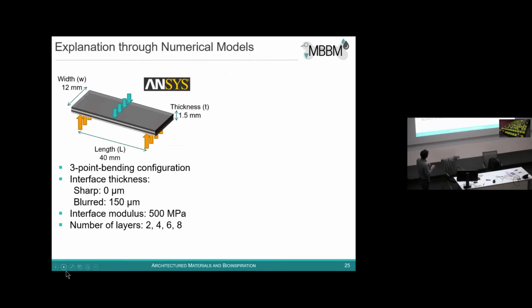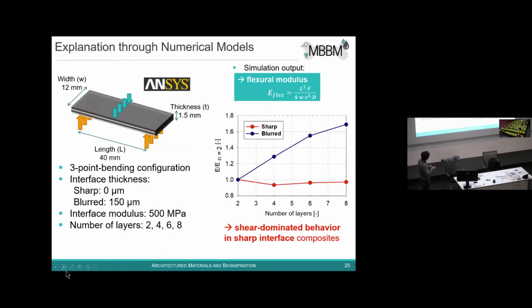So to understand this, we did some finite element simulations. We translate our system into a virtual material. We did finite element analysis, replicating the experimental conditions, and we considered sharp interface or blurred interface. And what we see is that in the case of a sharp interface, indeed, our simulation also shows no increase in bending rigidity by increasing the number of layers. So these are simulations with blurred interface, which were qualitatively similar to the experiments, and those are simulations of sharp interface, which are also qualitatively similar with experiments.